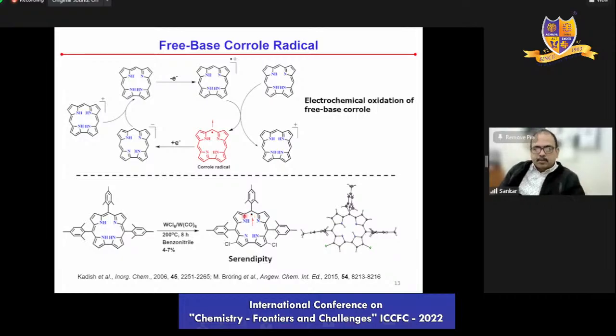Fortunately, they could get a single crystal X-ray diffraction structure. That means you take a compound, you crystallize it and put it in X-ray crystallographic diffraction measurement, and then you will be getting diffraction patterns. And when you solve the data coming from the diffraction patterns, you will be able to see the structure. This is one of the very common techniques used by most inorganic chemists. So they used the same technique to find out the structure of this molecule.